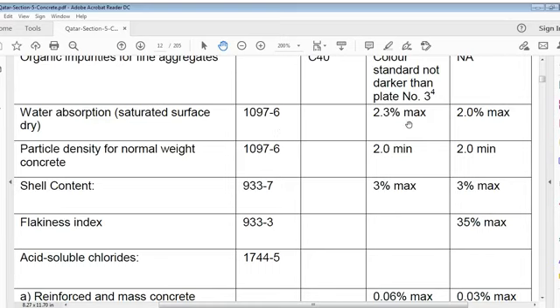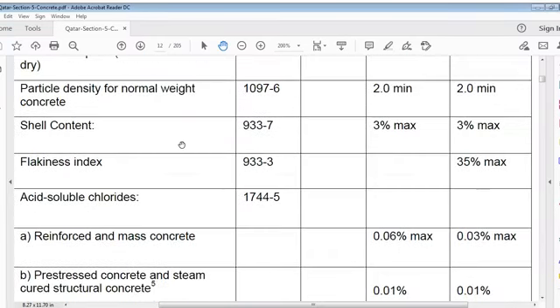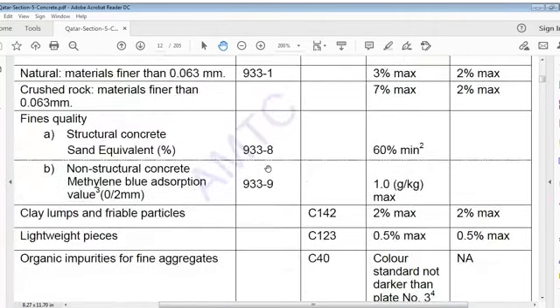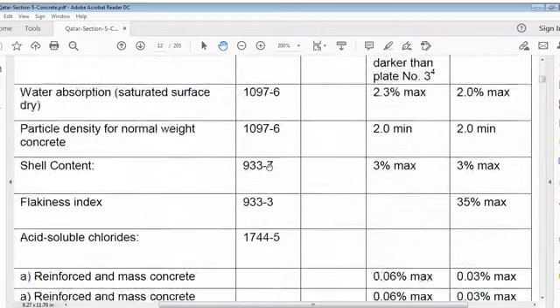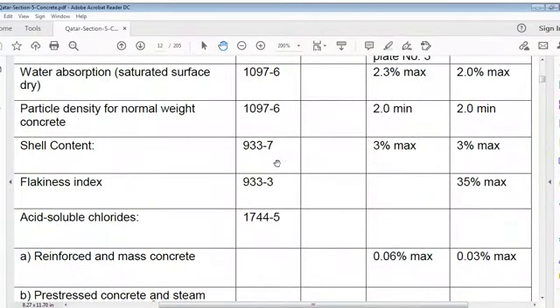Water absorption, saturated surface dry, 1097-6: 2.3% maximum, 2% maximum. Particle density for normal weight concrete, 1097-6, 2 minimum. Shell content, EN 933-7, 3% maximum.